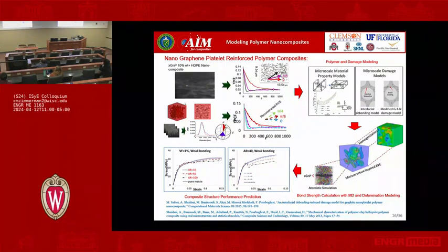For the resin, we know that this material is like a glue, but when you heat it and cool it, it changes what is known as crystallinity of it or something like that, and changes properties. So we take care of those, what we call viscoelastic material, Maxwell models and stuff. We put that in there to represent the glue or the resin part of it. We then put fiber properties in there, because if it is fiber or if it's graphene, we put the property in there. But more importantly, how do these things actually attach to each other? What is the strength, the bond between them?